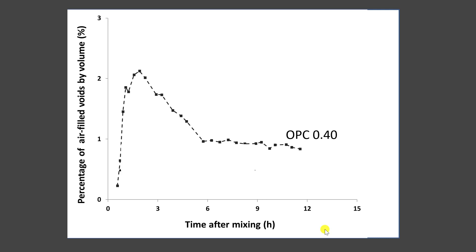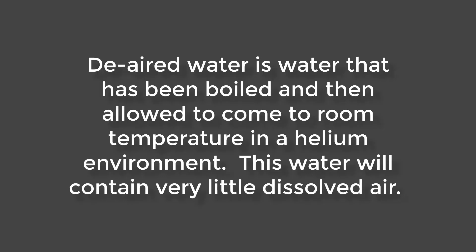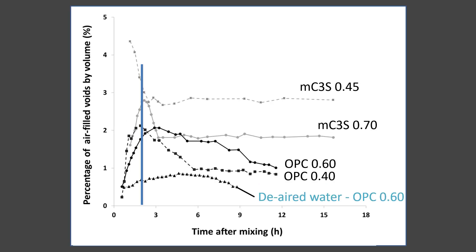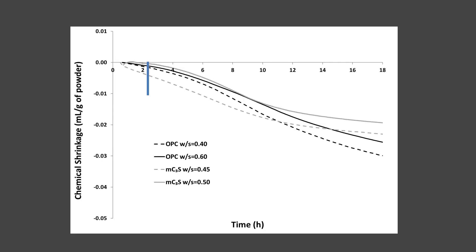Now if we use normal cement paste, this is what happens. If we use the same cement paste using de-aired water, things don't change that much. Now if we look at a lot of different mixtures from a lot of different cements, they all do the same thing. The air volume goes up, the air volume goes down, then it stays the same. But there seemed to be something magical happen here around two hours or so.